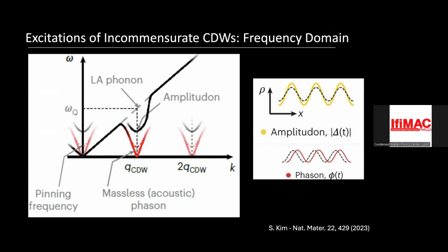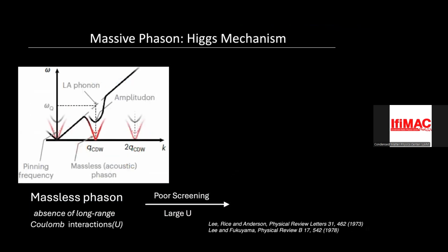It usually has no mass. And the way to understand it is to think about a 1D charge density wave, which is incommensurate. The fact that it's incommensurate is really important. That means it's not locked to the lattice in any way. The phase mode is just the shifting of the entire CDW in space, like this. There's nothing locking it to the lattice. It's very easy to move it, and so it has no mass. It has no resistance to motion. Okay? The amplitude mode, on the other hand, is always massive. All right. So that's what occurs in a normal charge density wave.